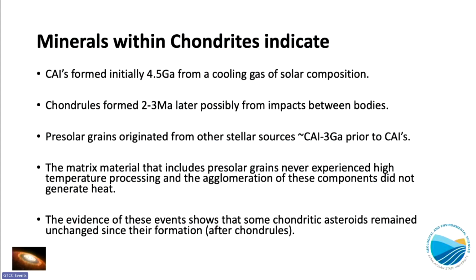So what we see from examining minerals within chondrites is that CAIs were definitively the first solids to form, and they formed from a cooling gas that has the same composition of the sun. We see that chondrules formed just a little bit later, or at least their precursors did, and possibly through the activity of impacts between bodies. We can see that presolar grains predate the formation of CAIs and chondrules and originate on the basis of activity from other stars. And we also know, I didn't talk much about this, but the matrix materials that include the presolar grains show evidence of not having ever changed in their lifespan.